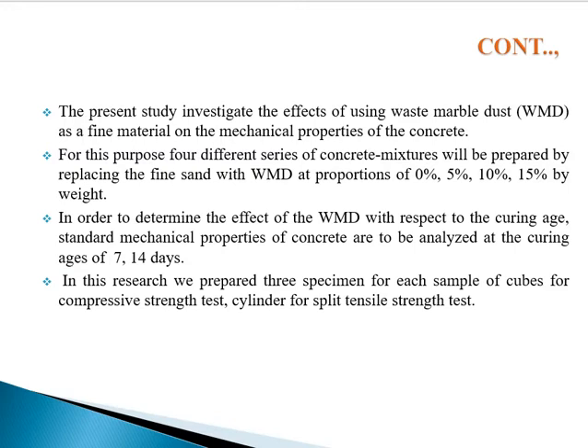For this purpose, 4 different series of concrete mixes will be prepared by replacing fine sand with waste marble dust at proportions of 0%, 5%, 10%, and 15% by weight. In this research, specimens were prepared for each sample — cubes for compressive strength test and cylinders for split tensile strength test.